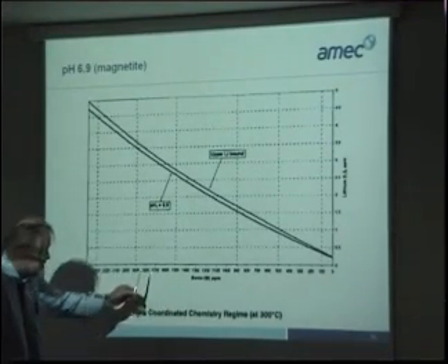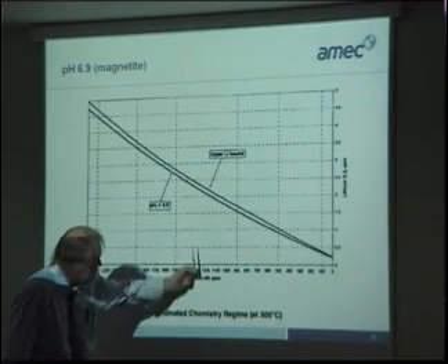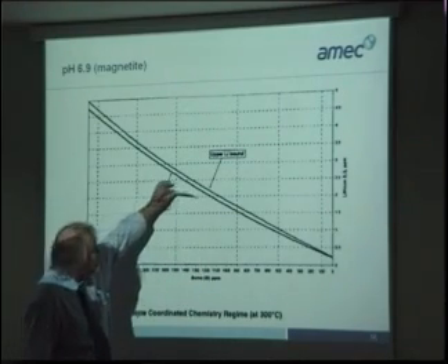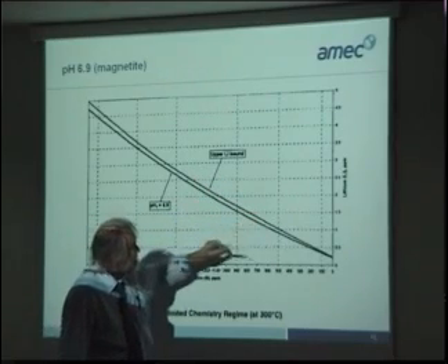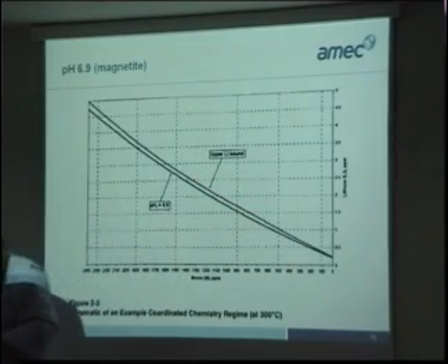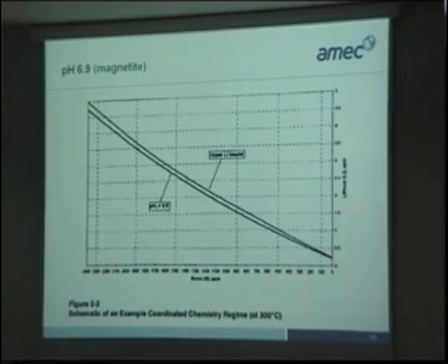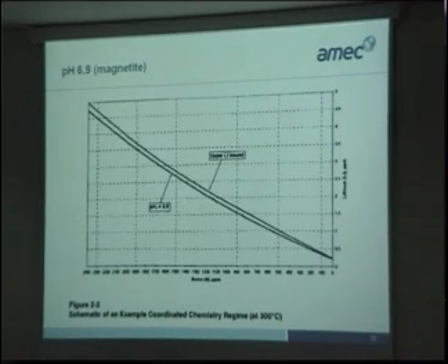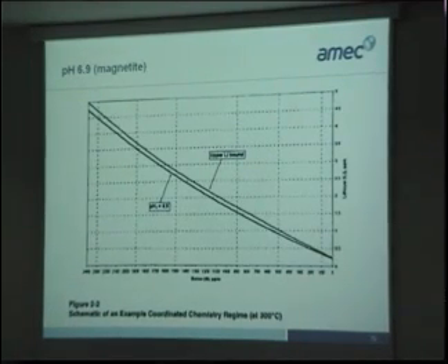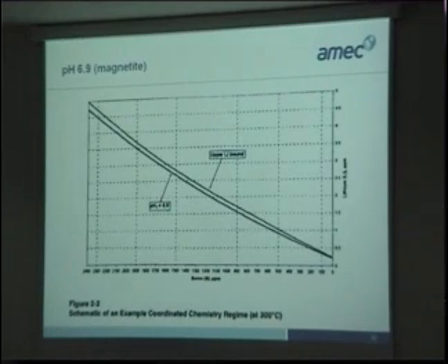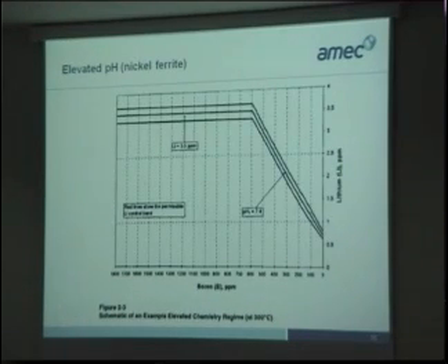But now, say at the beginning of the cycle, we might start somewhere here at 1200, 1100, and we'd coordinate this pH. So as we remove the boric acid to compensate for the reactivity in the reactor, we take out the lithium to follow the pH down. We have to take out the lithium because it's being produced all the time by the B10 N-alpha reaction. Nowadays, with more recent data, everything's based on the solubility of nickel ferrite, which is a substituted magnetite.